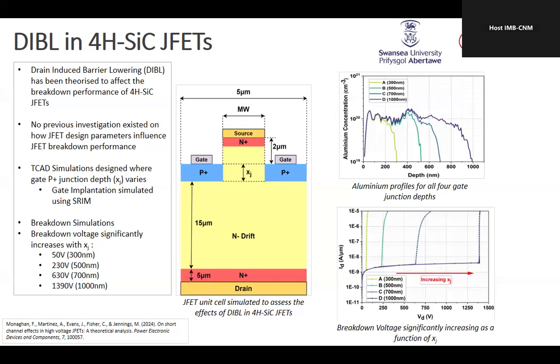So we found that is a limitation of this type of device. Also, the threshold voltage of such a device is very sensitive, as opposed to a power MOSFET in silicon carbide. It's very sensitive to the doping concentration in the drift layer, because in a real silicon carbide wafer, some suppliers actually, I know this sounds unbelievable, but you can have a 20% difference in active carrier concentration from one side of the wafer to the other side of the wafer.